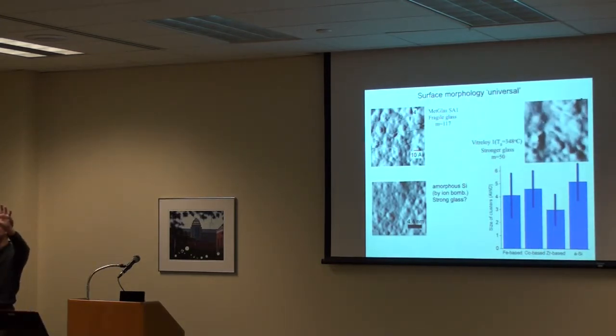Again, what the theory says is that when I have the liquid, the things that are moving are 1 atom in diameter because every atom can move anywhere at once, right? And as I lower the temperature, you start getting pairs and 3 and whatever moving. And eventually the motion gets slower as the viscosity increases and things have a tougher time getting past one another. And basically what that theory predicts is that universally when you reach a ball size of about 5, that's when things have gotten so slow that that's it and you're just stuck.